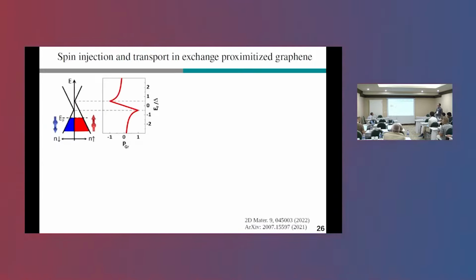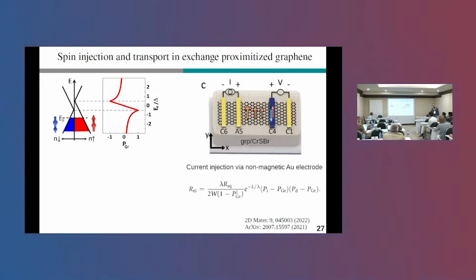Now why is this important? So this can actually be utilized for spin injection and transport. So when graphene is proximitized in the way I've shown, then the density of states will split up like this. And then the graphene polarization as a function of energy will follow this curve. And recent experiments by the Van Wees group exactly wanted to show this. So they did non-local spin transport experiments, which we have heard of today.